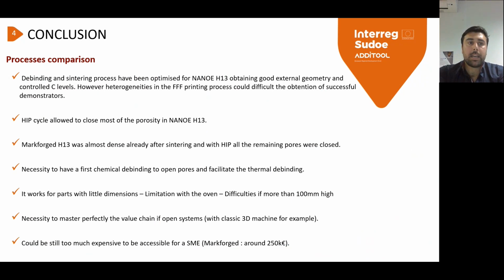So to conclude, the debinding and sintering process have been optimized for Nanoe H13 thanks to SEIT, obtaining good external geometry and control of the carbon level. However, we still have some heterogeneities in the printing process that can cause difficulties in obtaining a successful demonstrator. Something interesting also is that the HIP, hot isostatic pressing cycle, allows closing most of the porosity in the Nanoe H13 and also in the Markforged H13. Markforged H13 is almost dense already after the sintering, and with HIP we have 100% density, so very interesting.